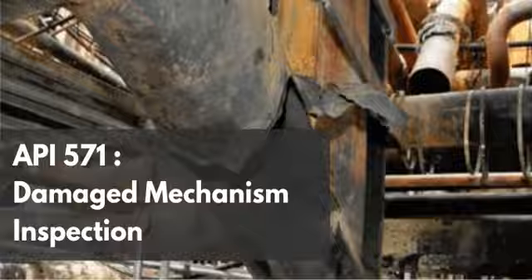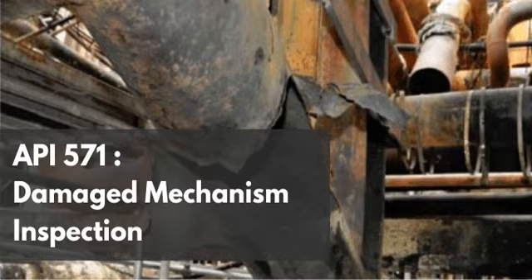And we really need to discuss the metallurgy of the cleaning process itself here. Because the text specifies a flapper wheel, which is made of overlapping flaps of abrasive sandpaper cloth, and implicitly warns against using aggressive hard grinding discs or heavy wire wheels. Why is that? Because the cleaning process cannot be allowed to alter the mechanical properties of the defect. Carbon steel, while strong, is also relatively ductile and malleable at the microscopic level.